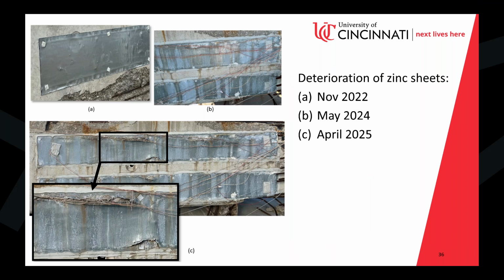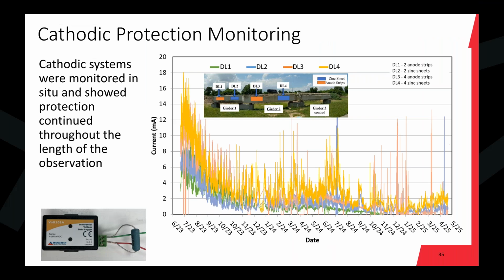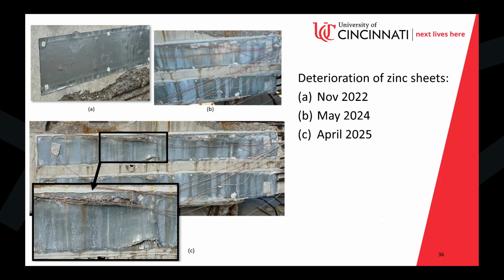So those were some of our major findings. Again, the difference between the strips and the sheets was relatively minimal in the previous slide, and accounted for simply by the amount of zinc that we applied relative to the size of the concrete girders. So everything worked as intended in this application with singular connections to the steel. So we were protecting all of the steel off a single connection, which is really important.